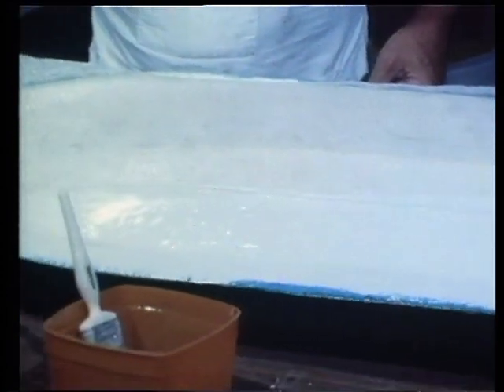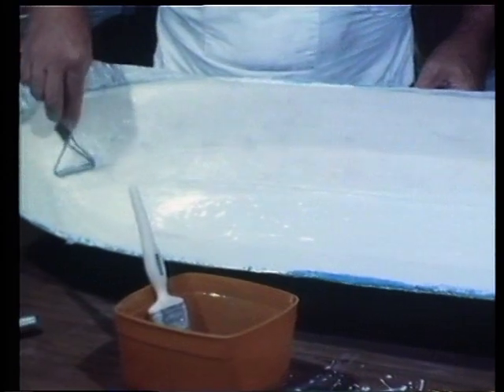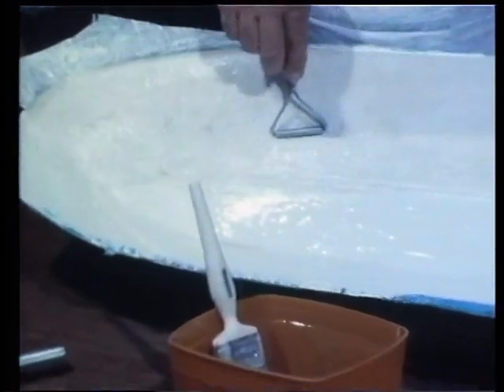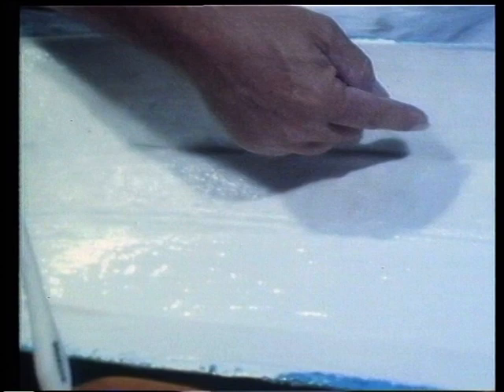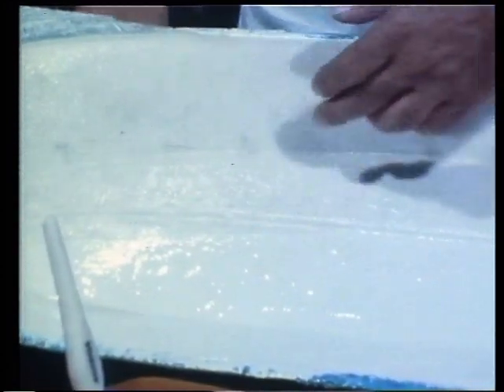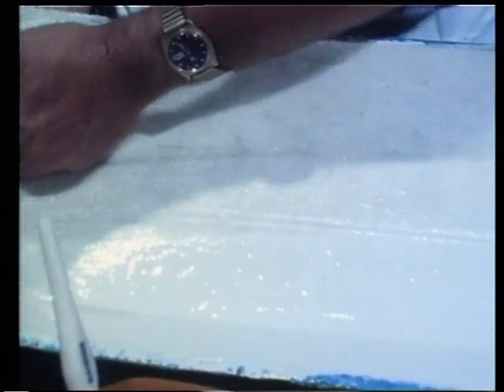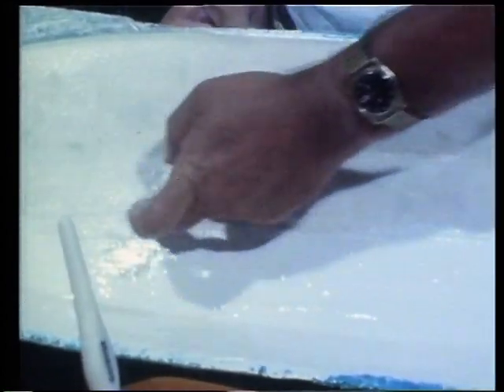If you look carefully, you can see the bubbles as little silver bubbles in the glass there, mainly because, of course, the resin is clear. So if you look carefully and with a little bit of experience, you can actually see the air bubbles down in the glass. Now, in this chine contour here, down here, we have a problem because that's a fairly tight little corner. It's difficult for the glass to get down into it. So in order to help it, we run our finger along and press it down.